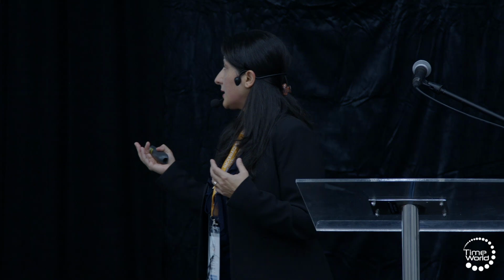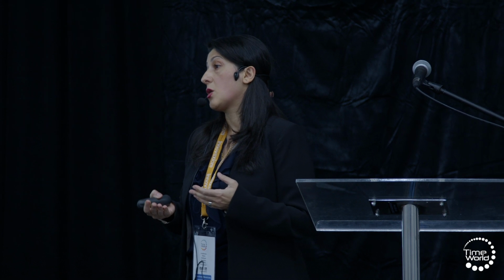So the problem here is that titania is the state-of-the-art material that we are using now. But if we use a bare titania sheet as a PTL inside our electrolyzer, we will end up with a passivation layer. So we will grow a passivation layer, and this increases the interfacial contact resistance, or ICR. So definitely we need the coating. What is the coating that people are using, or industry is using, or the state-of-the-art is platinum. So it means that we have platinum-coated PTL for electrolyzer. So another part that we need precious metal for electrolyzer.